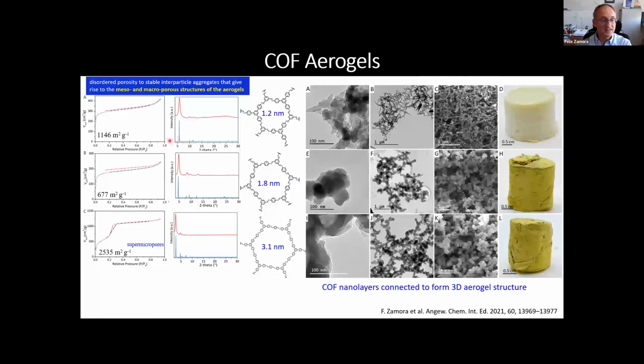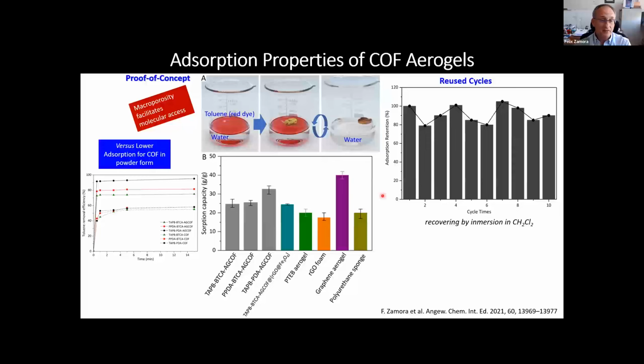And this is a slide summarizing the characterization, in which you can observe, on one hand, that we have materials with a nice porosity, combining mesoporosity with macroporosity. We have nice crystallinity with these three structures, and in here you can observe the characterization by transmission electron microscopy, in which you observe the nanolayers forming the 3D aerogel structure. And here, by scanning electron microscopy, you can even observe some of these macropores that you have in the aerogel.